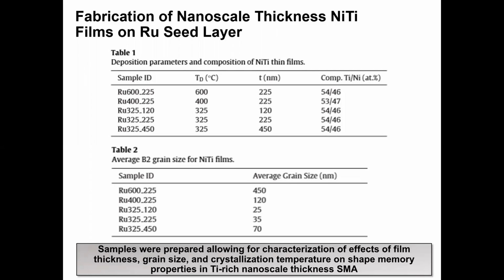The average grain size was measured in the B2 phase, as shown here in table 2, with a clear relationship of larger grains at higher deposition temperatures and longer deposition times. At the lowest deposition temperature of 325 degrees, the grain size increased from 25 nanometers in the thinnest film up to 70 nanometers in the 450 nanometer film. The largest grain sizes were measured in the 400 and 600 degree films, and this is consistent with the understanding that grain growth, or in other words, grain size, has a strong temperature dependence.